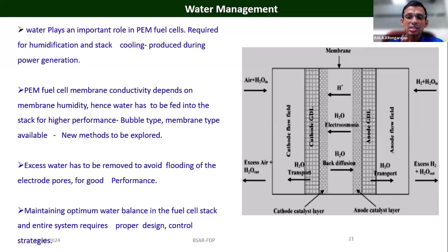So this membrane will act as a gas separator, keeping the gases in different compartments, and it also acts as a proton exchanger from the anode compartment to the cathode compartment. This is a kind of electrolyte which will take care of the ionic movement between the electrodes. Proton conduction is effective only when the membrane is fully hydrated. So the membrane has to always be in wet condition so that effective proton transport takes place between anode and cathode. But at the same time, if you allow more water retention within the system, it will create flooding in the entire system. So you must have effective water management within the fuel cell stack, or otherwise it will degrade the fuel cell performance. Water has to be there, but it should not exceed the limit. You have to constantly remove the water which is produced at the cathode compartment.